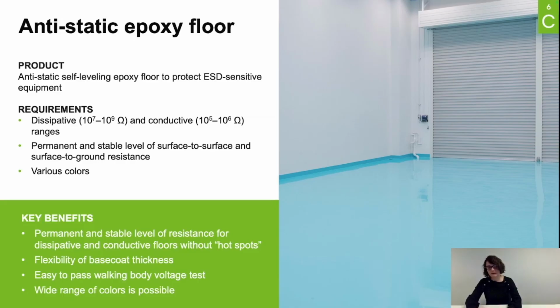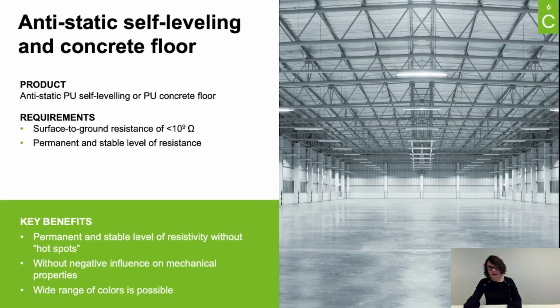So a stable resistivity without any hotspots. So basically the resistivity obtained in one point of the flooring through the other one is exactly the same. They could obtain all the local norms that they were looking for, and of course they were able to design it in a full variety of ranges. If I'm not mistaken, I think they had more than 15 shades available. So TUBALL Matrix 301 will allow you to design epoxy floors, but not only.